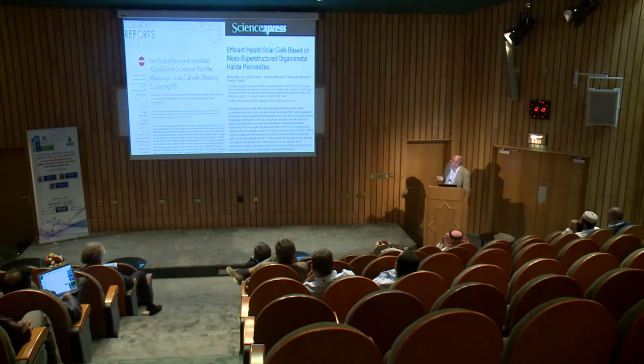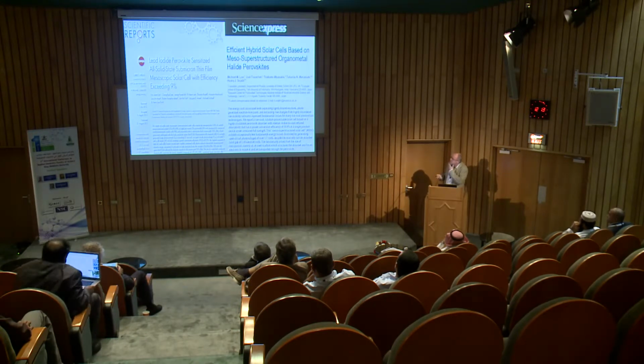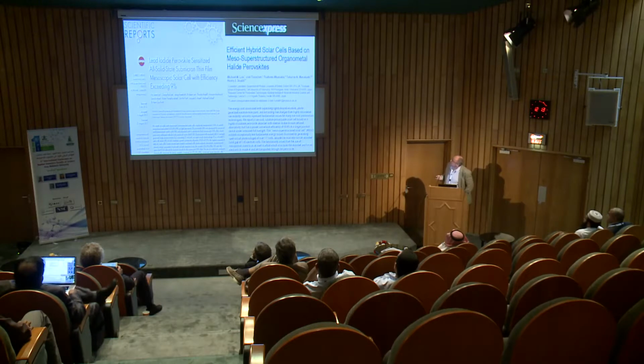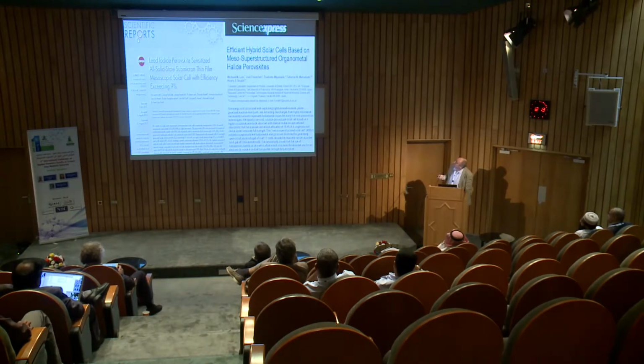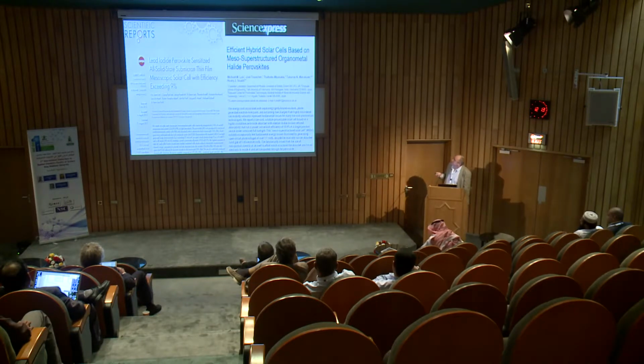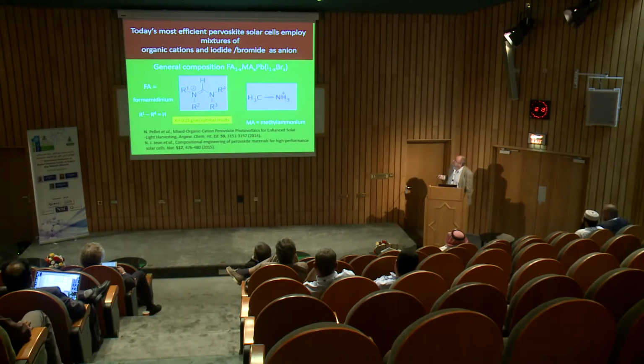The breakthrough came then, two parallel independent works. Henry Snaith at Oxford contacted Miyasaka to ask if we could work on solid-state hole conductors with the perovskite, and asked for the recipe. And Nam-Gyu Park contacted Miyasaka to ask the same thing, basically. And then in parallel in 2012 it was published about 10% efficiency using perovskite and the solid-state hole conductor. And that has really created a huge amount of interest for the moment.